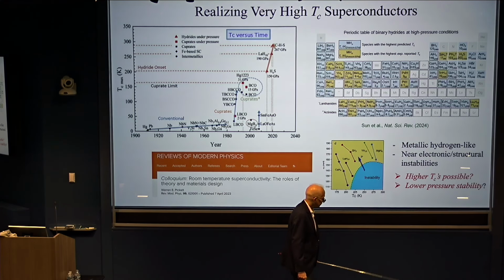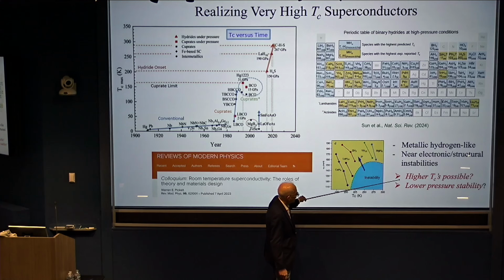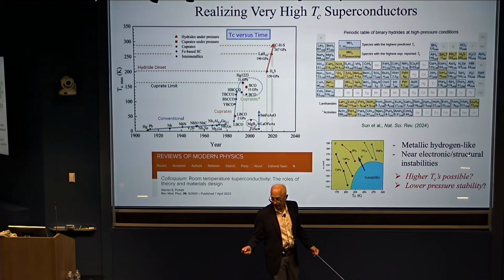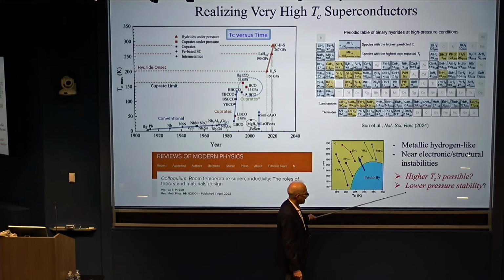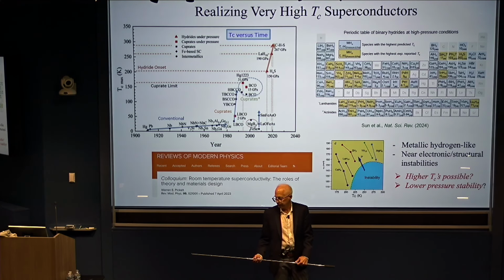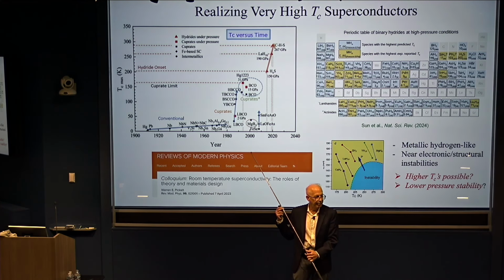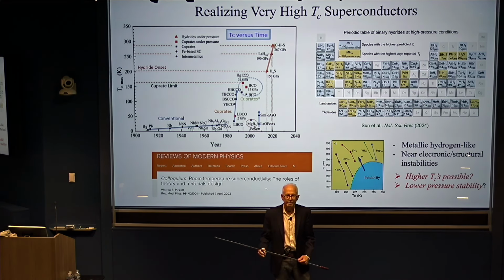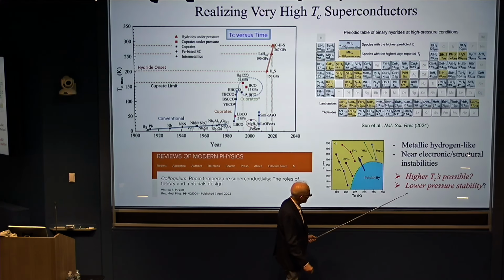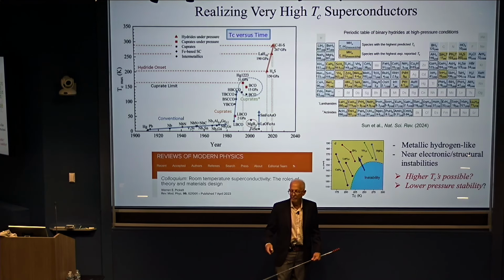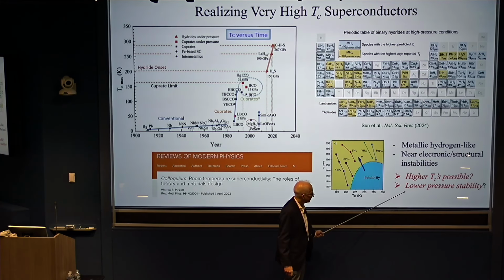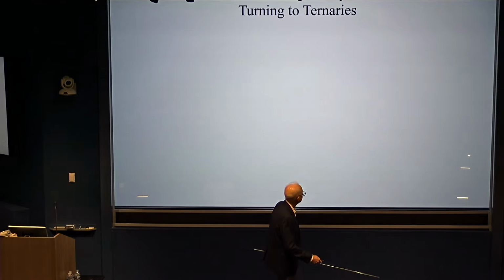But there are interesting questions now. Can we get to higher TCs? In fact, is there a limit on the superconducting temperature? And also the very important technological question, these are stable only at very high pressure. You cannot recover them to ambient or near ambient. Is there lower pressure stability? Can we learn something about these by changing the chemistry or somehow the synthesis conditions so that we can have low pressure, at least kinetic stability for these materials?